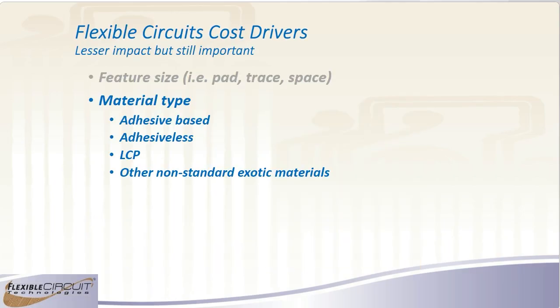Material types. For our base laminates, we can get adhesive-based, where the copper is held onto the dielectrics with a thermosetting adhesive. We can also get adhesive-less, which is a little bit more expensive. It's getting better, but those are better for higher temp applications because you don't have any thermosetting adhesive. LCP, I typically try and steer people away from that because it is very difficult to use and it's expensive. And now with the other materials that give you the low loss features, you're better off going that way.